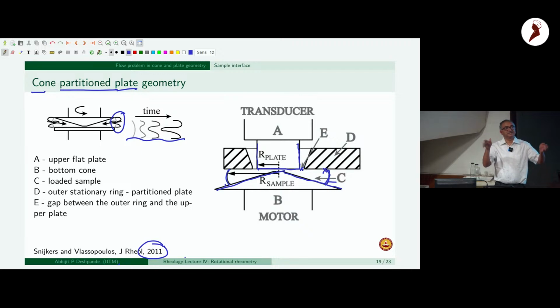But regarding the interface being not spherical, I'm not sure that just because particles are there, it will lead to that, because the particles are so small compared to this scale. In cone and plate, you should look at only those systems which are 5 microns and smaller. Then they are small compared to the perturbations they cause to the interface, which is still going to be small.